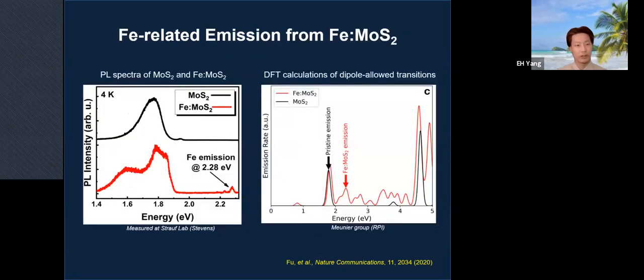So the PL spectra shown on the left shows the undoped sample, which is in black, and the doped sample, which is in red. And you see this iron-related emission at 2.28 electron volts, right? eV here, only from the iron-doped sample here. And this was further corroborated by DFT calculations of dipole-allowed transitions. Again, what is shown here is direct iron-doped molybdenum sulfide emission from this modeling that matches the experiments, okay?